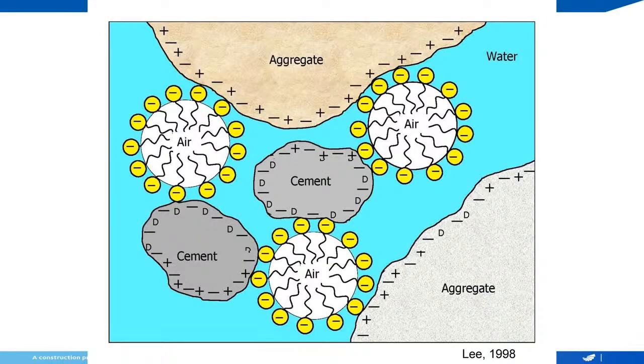Sorry. And then you've got the water, you've got all these materials, and air needs a really stable home life. So for air to build and then to stay stable, it needs a stable home life. And we'll talk more about individual aggregate materials later, but that whole mortar phase of the mix, that material passing the number 8, that's where the air lives, and in particular those areas between the 30 and the 100 sieve. So we need that material in there to give that air a stable place to live. The other thing that impacts that, again, that we'll talk about later, is the rheology of this mix. And I'm sure some of you are doing self-consolidating concrete, and that presents its own set of challenges.